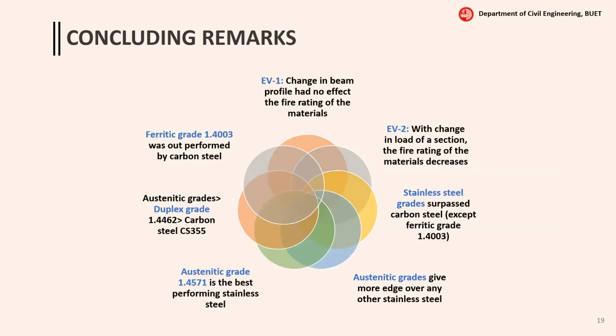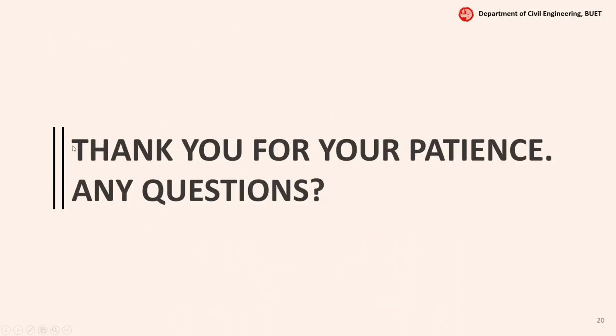So concluding remarks. From our evaluation criteria 1, we saw that change in beam profile had no effect on the fire rating of the materials. In evaluation criteria 2, we found that with change in load, the fire ratings decrease. In all the cases, stainless steel grades surpass carbon steel except the ferritic grade. Austenitic grades were the best among the stainless steels. Austenitic grade 1.4571 was the best performing stainless steel. The performance of duplex was between austenitic and carbon, and ferritic was outperformed by carbon steel. Thank you for your patience.